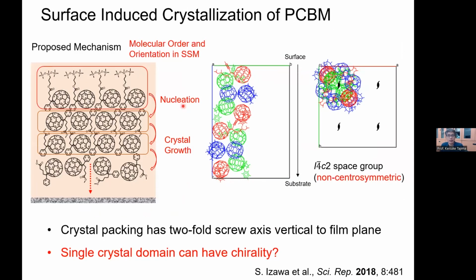Here is what we think is happening. The oligosiloxane version molecules have a certain orientation, with the fullerene pointing down, and this molecule nucleates the crystallization here, and crystal growth propagates from the surface to the bottom. That is what we think. Another thing we notice by looking at this crystal structure is that there is a screw axis in this direction. This is the top view, so it's a kind of helical structure of the fullerene.